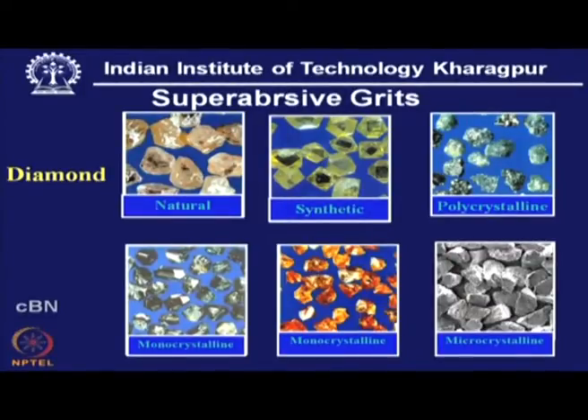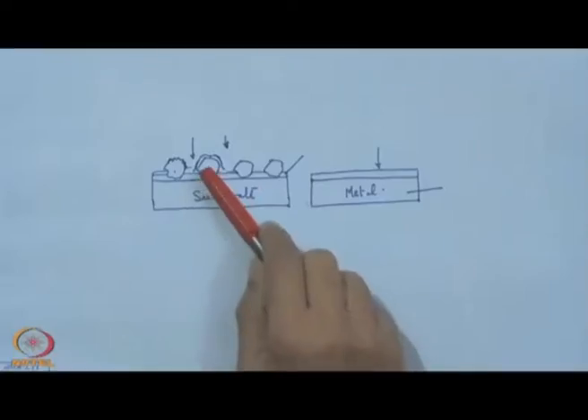It is actually removing those metals which remain on the surface of the diamond during the process of synthesis, and that has to be etched out, and this etching process becomes a part of the preparatory step to tailor these crystals for this electro deposited anchoring. There can be another way of doing the thing, there are certain processes which are practiced in industry. That means these crystals are coated with a non-conducting coating like a plastic coating, and then the so-called conducting grit loses its conductivity, and without any difficulty that can be used for anchoring on this surface.